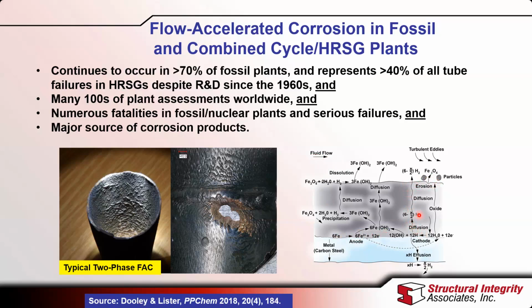And I'm not going to go into too much more detail about it, but this is increased by the turbulence, by the bends at the top of the low pressure evaporator, typically, or some geometrical feature that helps to remove these particles from the surface. And that's essentially what FAC is.